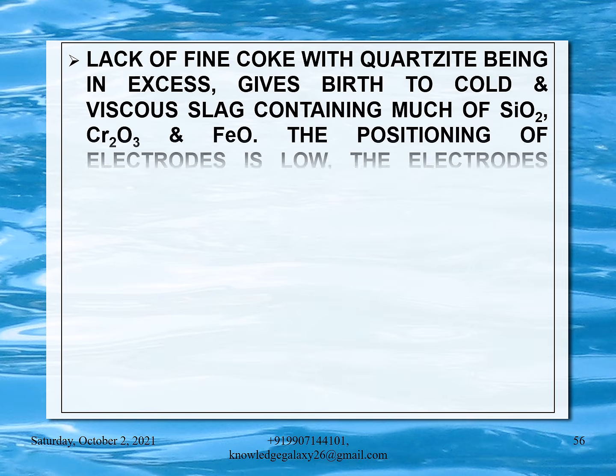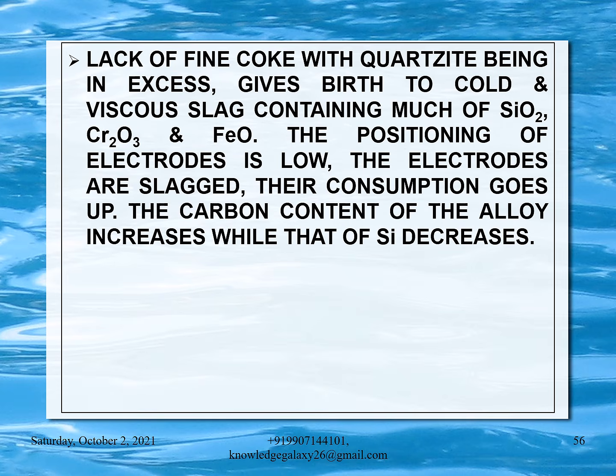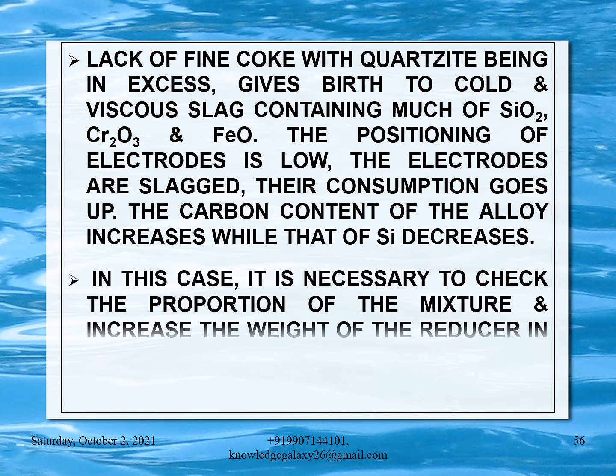Lack of fine coke with quartzite being in excess gives birth to cold and viscous slag containing much SiO2, Cr2O3 and FeO. The positioning of electrodes is low. The electrodes are slagged. Their consumption goes up. The carbon content of the alloy increases while that of silicon decreases. In this case, it is necessary to check the proportion of the mixture and increase the weight of the reducer in the mixture.